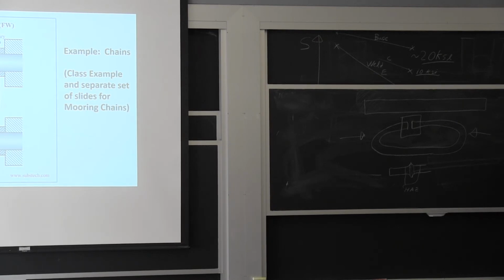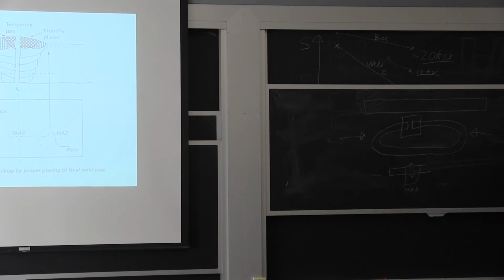When you do it and you're done, the main advantage is you created so much heat. You use that for railroad tracks too, a version similar to this. You generated so much heat that you're not going to have a cooling rate that's tremendously high. So you can take relatively high strength steel and go through this whole process without forming martensite. But if I try to do it the more manual way and have all these beads, I could be left with very, very high hardness in the heat affected zone.